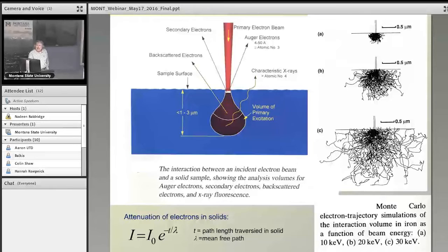X-rays can penetrate deep. So X-rays can come out of here, and will tell you information about the bulk inside. 1 micron is 1,000 nanometers. It's a huge distance as compared to the surface. And this is a 1 nanometer wide beam, and this is a couple thousand times bigger than that. So in reality, this should have been huge, if I drew things to scale. Most people think 1 micron is a surface. Wrong. 1 atom is a surface. When we say it's surface sensitive, I'm talking about 1 atom thick.